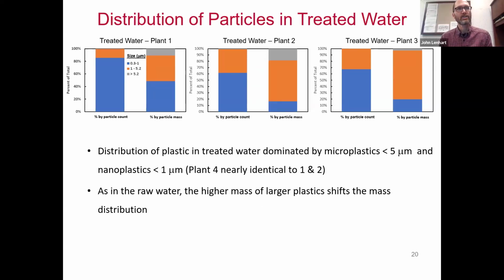We look then at the treated water, and the treated water shows similar trends in terms of the particle concentrations, with the counts of particles being dominated by the nano and microplastics, and then a small signal associated with the presence of the larger size plastics when you look at it in terms of mass. So in most instances, there are very few larger plastics getting through treatment. And of those, they're on the order of 5, 6, 7, 8, 9 microns, very small. We're talking just a handful of these particles, but their larger masses change the distribution in terms of the percent of the total.